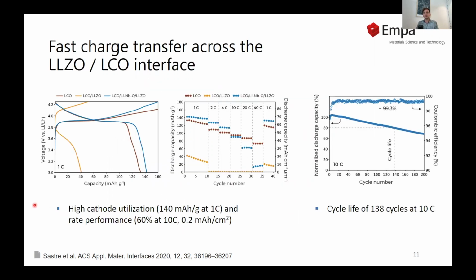We also investigated the charge-discharge characteristics of these half cells consisting of LCO and LLZO and compared it to bare LCO in liquid electrolyte. What we observed is that an interface modified LCO-LLZO half cell is capable of delivering about 140 milliamp hours per gram, which is close to the theoretical capacity of the cathode, whereas the non-modified LCO-LLZO half cell delivers less than a third of the theoretical capacity of the cathode.